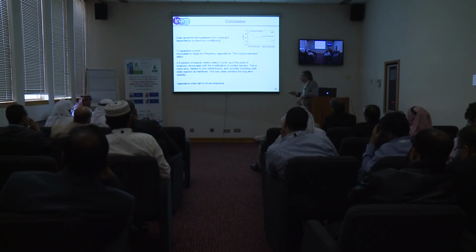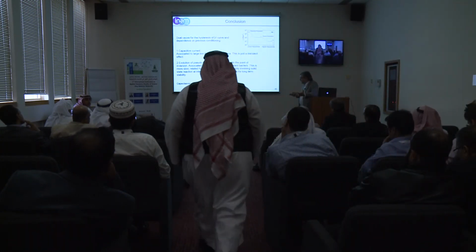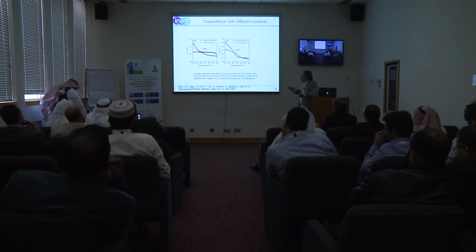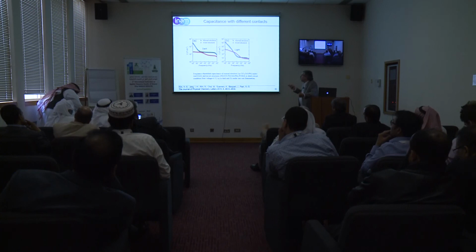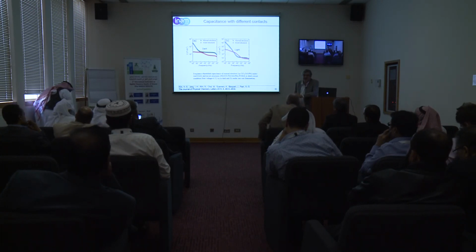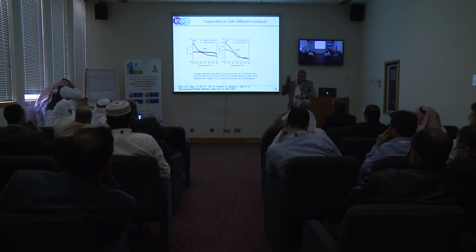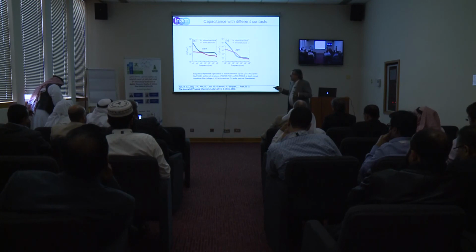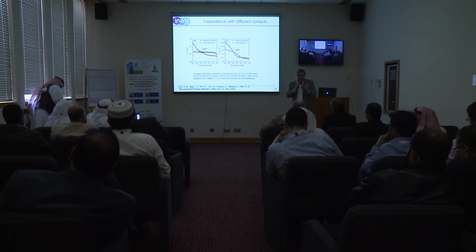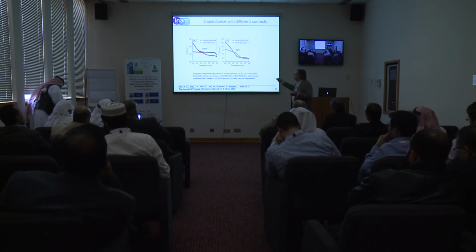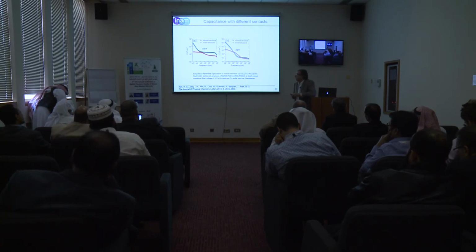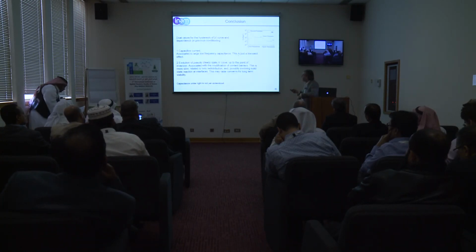The capacitance, we have studied in the dark and it has been well understood. You can see that under light it goes from microfarad to millifarad. Millifarad is very big. So what is that? I do not think this is ionic capacitance, like electrode polarization. When you put light, you have 1,000 times more, and this cannot be ionic. So somehow the electrons are going there. Okay, so we will see. That will be the next part of the study.